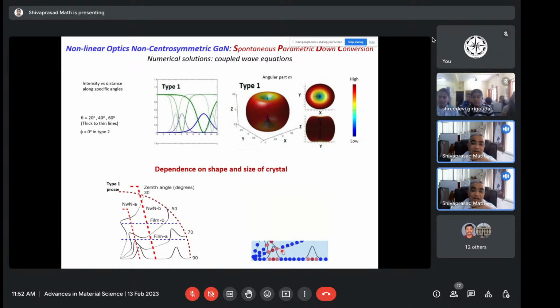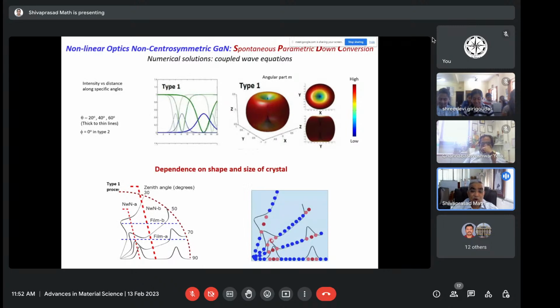And now, interestingly, if the light travels longer in this material, it will again get reconverted into blue light. And that is why in the normal condition, we may not be able to see it. But now, by making these films cut at this particular angle, as you can see here, where it is red, it has already made this conversion, I can get that light out of it. And that was the second peak I was seeing in our cathodoluminescence experiment. And that is, I think, very important. So instead of the bandgap emission which was in the ultraviolet, now we are getting a radiation in the infrared, which is very close to the 1553 nanometers, which I talked about.